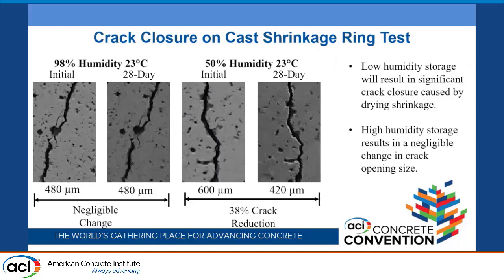What we found is that when we stored our samples at high humidities, we were not seeing that crack closure, just because shrinkage had been abated. But when we stored them at ambient conditions, we were starting to see crack closure again. This is more a testing procedure question—we can't test the samples, leave them out for a day, and then test them again. We need to be very precise in our processes.